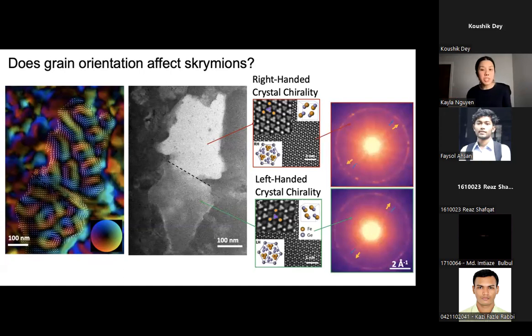We do another check where we look at the diffraction pattern, and within the diffraction pattern, you can see that we get very thin bands on the left side and a wider band on the right side. The opposite is true for the bottom image. We get the wider band on the left side and the thinner band on the right side. So what we find is that skyrmion vorticity, or the curl of the skyrmion, is aligned with the crystal chirality.